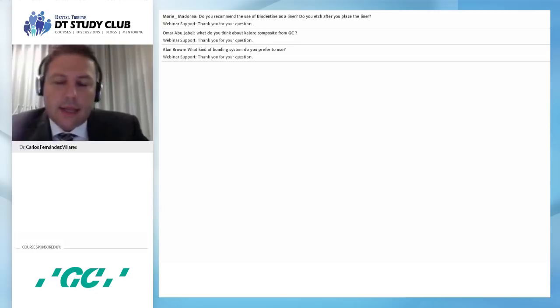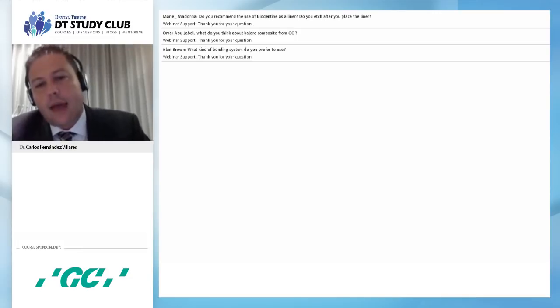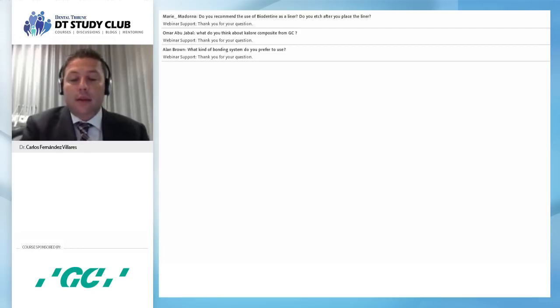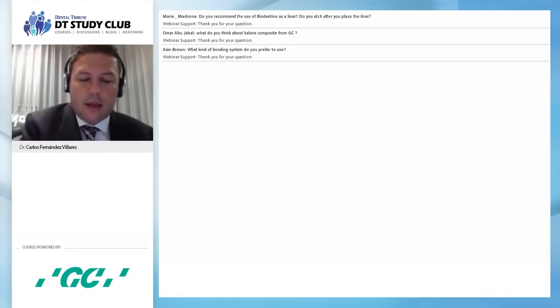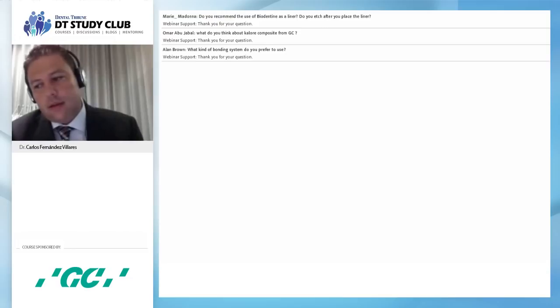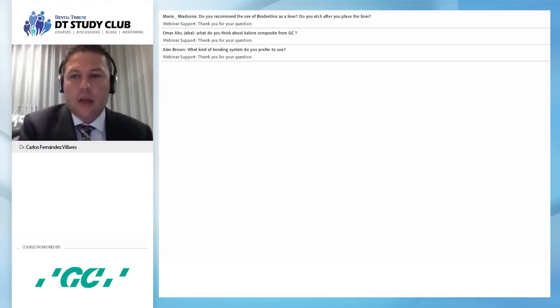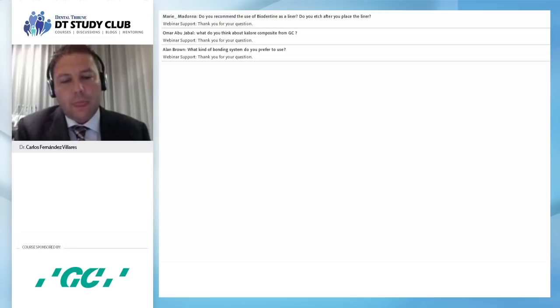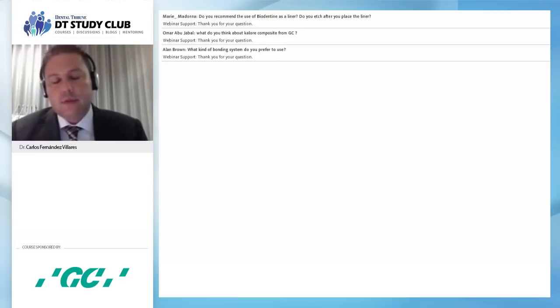But as I said during the lecture, the most important thing for me is to know the material I'm using and try to use it in the best way. So I don't care if I use a two-step system or three-step system, I try to follow the steps to obtain the best from the adhesive system that I use. But if I have to make a résumé, I would always use a universal self-etching system in the posteriors, and in anteriors I will use etching and primer and bonding in a separate way.